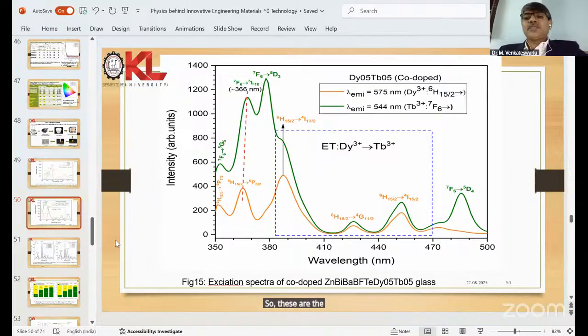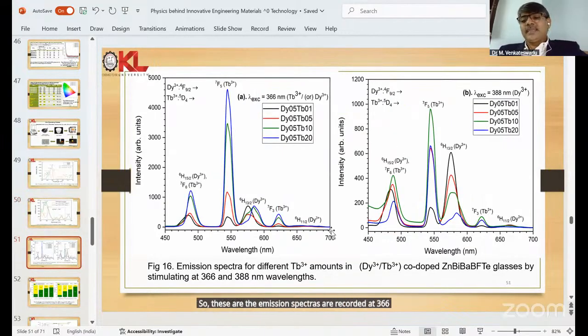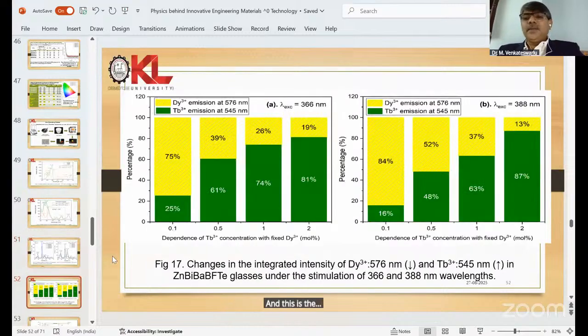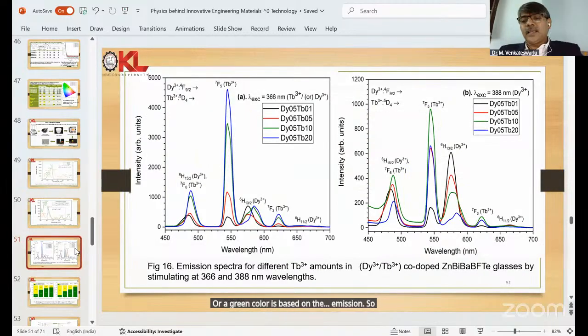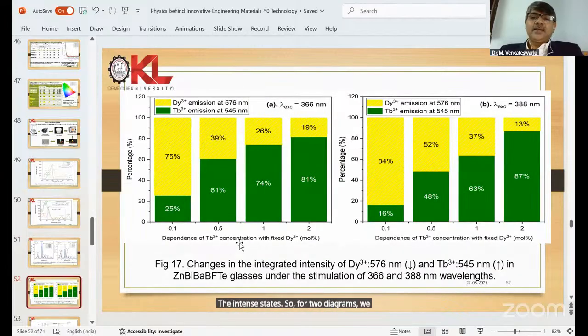So these are the emission spectra recorded at 366 as well as 388 nanometers. You can observe that at 366 nanometers we are getting the maximum intensity when compared to this. And this is the Y by B ratio. Here yellow to blue, the green color is based on the emission. So this one is the yellow and this is the green. Now these ratios we have taken from the intensities, for the two diagrams we considered at 366 as well as 388 nanometers emission spectra.